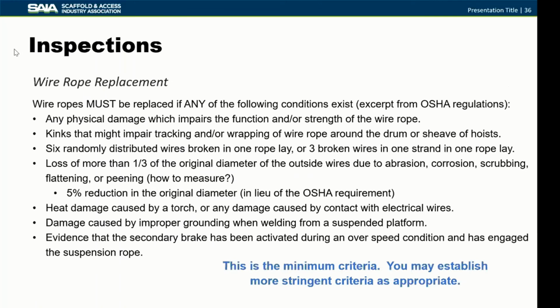And just to reiterate, looking at what OSHA says you have to look for when you're doing an inspection on wire rope: any physical damage of the wire rope that might impair its function or strength, kinks in the wire rope, 6 randomly distributed wires broken in one rope lay, or 3 broken wires in one strand. I know a lot of people have a significantly tighter criteria than that, but that is the minimum from OSHA.